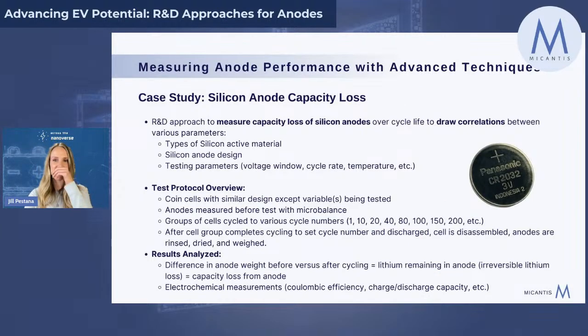So now I'd love to talk more specifically about a really cool research technique that was used for silicon anodes. And this is to measure the capacity loss over time with anodes, but it could be used to do much more than just that. So I'll let your scientist brain think through maybe how this could be applied in your system, especially if you're using an anode material that as you're cycling it, there's a weight gain in the anode and or on the cathode that you can actually measure with the microbalance.